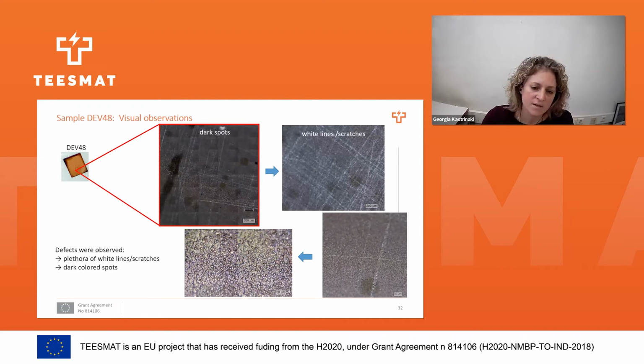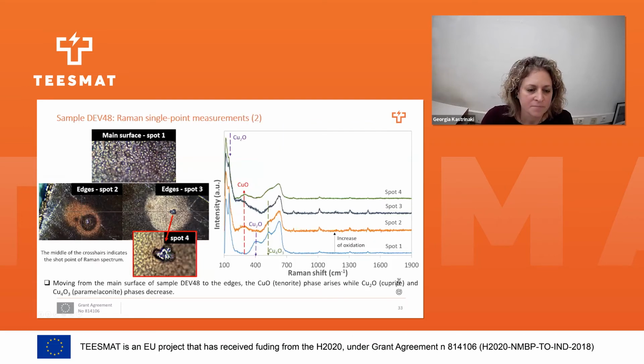So from morphology, we can see that we can have different kinds of colors, and here we can have some dark spots and also some white lines. And if we go to higher resolution, we can see exactly how it looks. And we tried to compare the different kinds of spectra obtained from different regions. So here you can see that this is probably a problematic region that needed further study. So we have here a source of oxidation, and this causes different colors as we move away from the source. So we took spectra from the different spots.